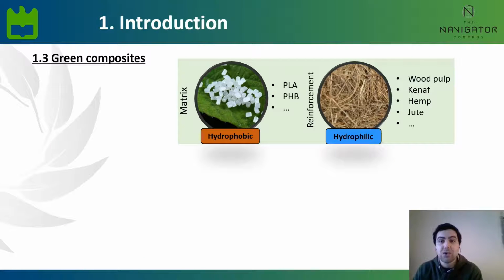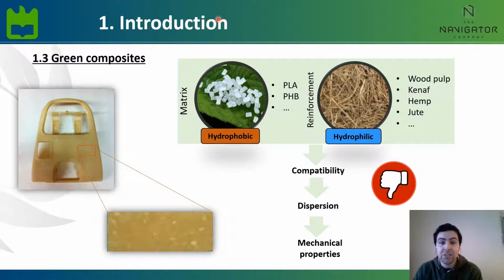Nonetheless, these so-called green composites, where both the matrix and reinforcements are bio-based, face some of the same challenges as the biocomposites. Because the matrices are hydrophobic and the cellulose fibers are hydrophilic, this intrinsic hydrophilicity of the fibers combined with their high aspect ratio often leads to agglomeration and bad dispersion of the reinforcement in the matrix. And as a consequence, the visual aspect of the composites is inevitably impaired, as well as their mechanical performance.